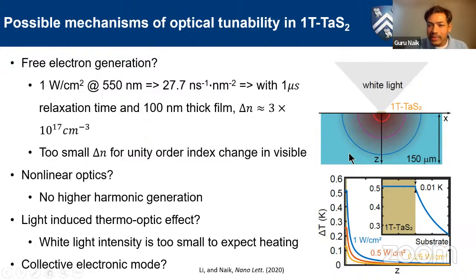Then we did build a thermal model. We don't have, of course, the thermal conductivity of a lot of things here, but we gave some freedom and chose the most lenient thermal resistances so that we can find out the maximum possible temperature rise in our sample. And even with the most lenient parameters, we got about 0.5 degrees centigrade as a maximum temperature change in our sample, which is still too small to expect a unity order index change. So the remaining option is simply to suspect that it's something to do with CDW.